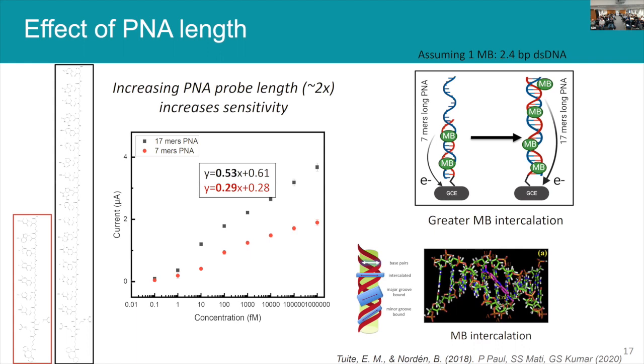So this is a calibration curve for the 7-mer in red, and we did exactly the same thing. So different concentrations of microRNA, but now with the 17-mer, and you can see this really nice increase in sensitivity quantified by the slope of the linear regression line. If you fit a linear regression line, your slope comes out to 2 times greater, which is wonderful, and that also reduces our limit of detection.